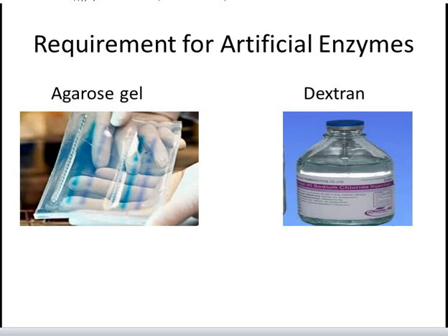Agarose gels are composed of a 3D network of hydrophilic thick fibers 20 nanometers in diameter, much larger than the protein sizes, around 2 to 3 nanometers in diameter. Thus, proteins and other macromolecules become immobilized on large internal agarose surfaces. Such support geometry becomes a key feature in order to get very intense enzyme-support multi-point covalent immobilization. On the other hand, such support geometry may be suitable to permit the adjacent immobilization of the polymers surrounding the previously immobilized enzyme. In this way, the co-immobilized hydrophilic polymer may fully protect a great portion of the surface of the immobilized enzyme.